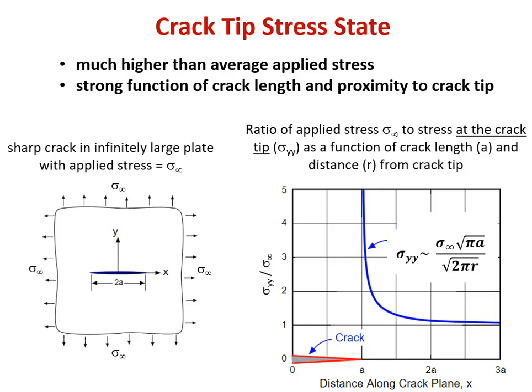But if we started walking closer and closer to the crack, this is an imaginary scenario where we're walking through a crystal lattice, basically, as we got to within 1a of the crack tip, approaching it, our actual stress state would start shooting through the roof. And the ratio of the stress state we would be experiencing at that location compared to the bulk applied stress, the stress infinity, would be the square root of pi times the crack length over the square root of 2 pi times how far away from that crack tip we were, out in front of it. So we're seeing now a dependence. The localized stress state in front of that crack is dependent on the length of the crack and how far away from the crack we really were. So the closer we are, the higher the stress, and the longer the original crack length, the higher the stress relative to whatever we applied.